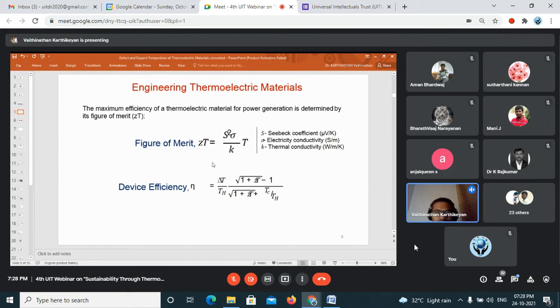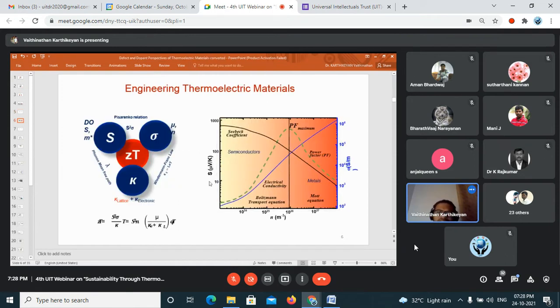Okay. The next graph tells what the expected electrical conductivity will be, in terms of Siemens per meter, for a given carrier concentration, and that curve is the Seebeck coefficient. You can see the Seebeck coefficient value drops as the electrical conductivity value increases. The blue line is electrical conductivity. And you have a point where the power factor, that is the numerator value, is at a maximum. This is what everyone wants to achieve in the material. And here the n corresponds to the carrier concentration, the number of electrons or holes in the material.